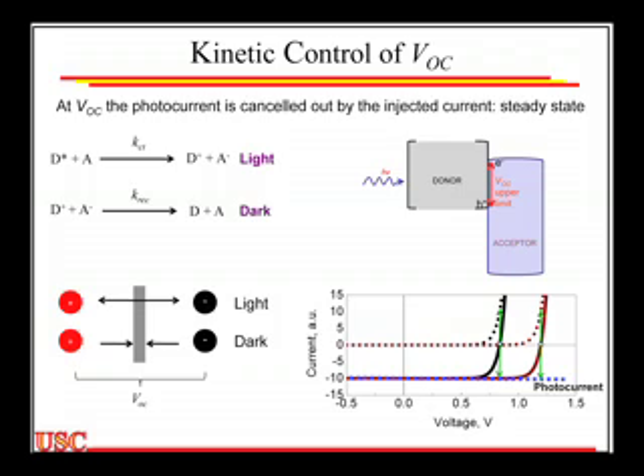So the question then is, the maximum open circuit voltage I can get is given by this energy difference, but we never get that. So what limits how close we get? I'm showing you here two different imaginary curves. The one in black, you can't easily tell black versus red, is a high dark current, and this is a comparatively low dark current. Remember, the photocurrent is the same for both of these. The open circuit voltage occurs when the photocurrent exactly equals the dark current, which you can see for the high dark current happens at a much lower voltage than for the low dark current.